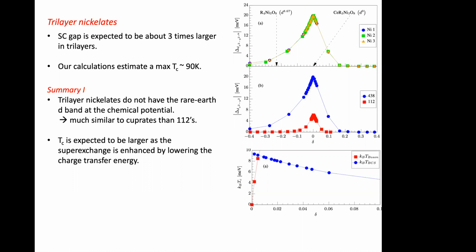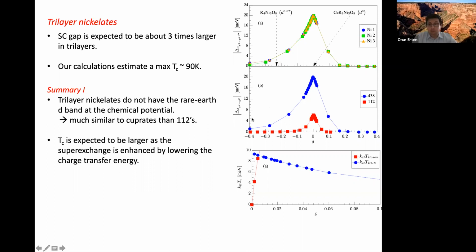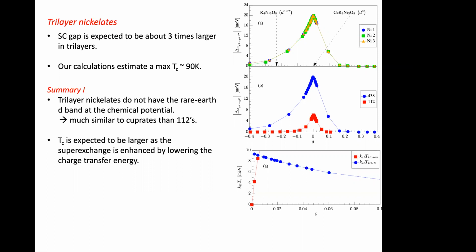What about magnetism? So magnetism, we anticipate magnetism to arise if you can actually electron dope the system and go to nominally half filling. But most of the studies are, because the parent compound is not really D9, it is self-doped away from D9. And if you really want to observe magnetism, you need to go to the anti-ferromagnetic Mott-insulating limit, which in this case would arise in electron doping. But there's not many experiments there.